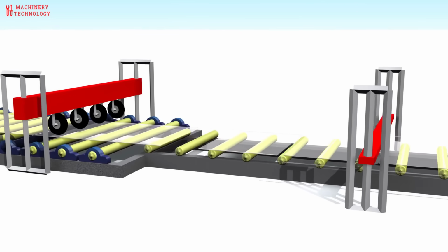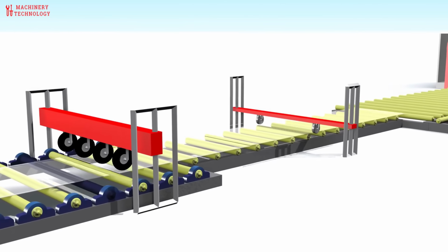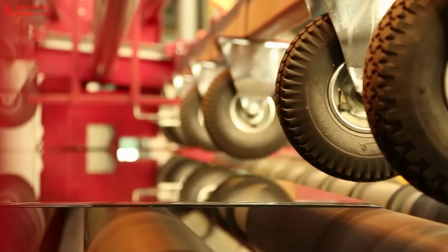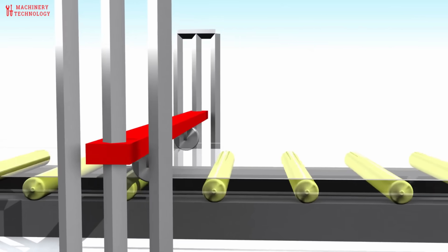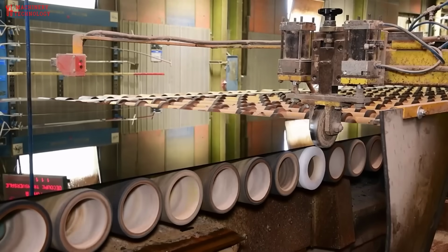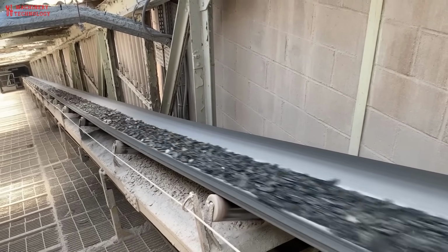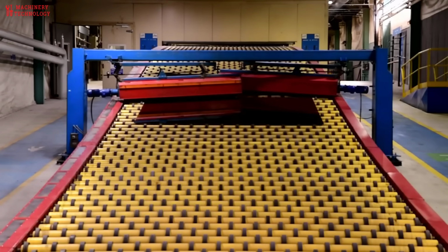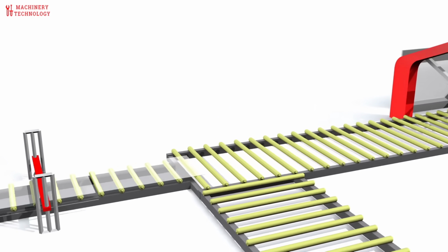In the breakage area, the continuous ribbon is interrupted to form glass plates. The breakage operation consists in a lever effect made by an automatic breakout bar aligned with the transversal cutting line. Next, the edge rollers apply a pressure on the longitudinal cutting lines to trim the glass plates. The edges, together with any glass area not fulfilling the required quality standards, go back into the furnace for recycling. The plate thus formed is then carried by rolls at higher speed to separate it from the continuous ribbon.